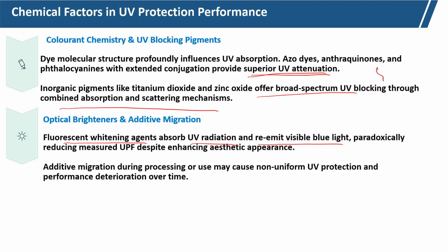It is fluorescent, so it emits visible blue light. After absorbing the UV ray, it emits the visible blue light, which paradoxically reduces the measured UPF despite enhancing the aesthetic appearance. That is very important.